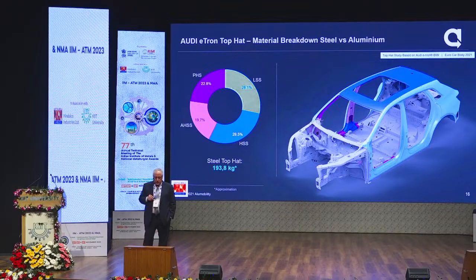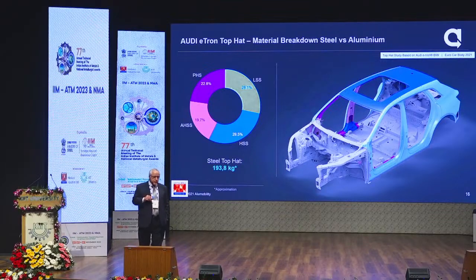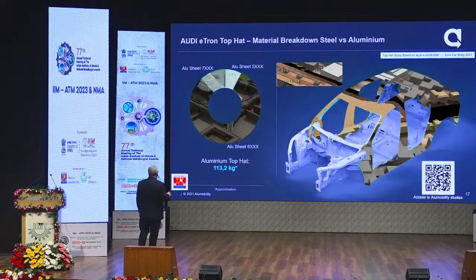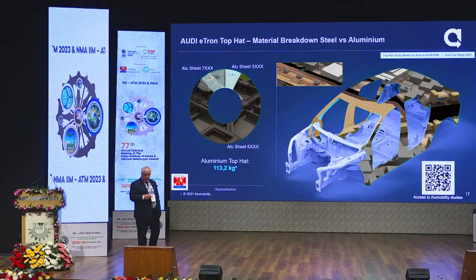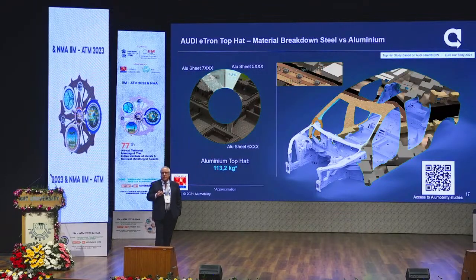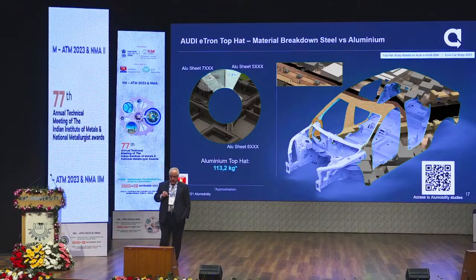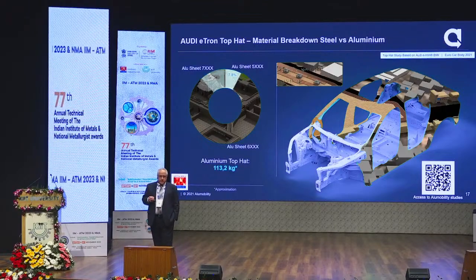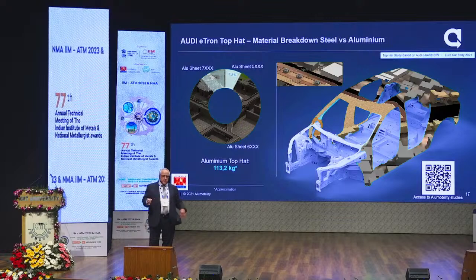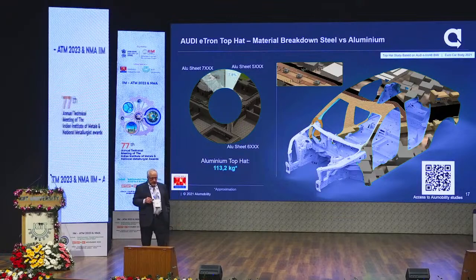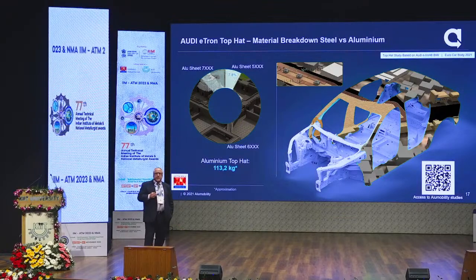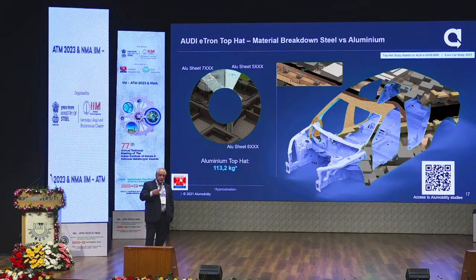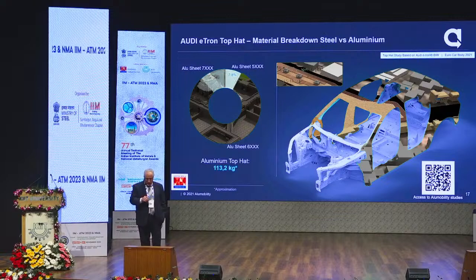First example, Audi e-tron top hat, super optimized in steel grades, 193 kilo for this top hat. Moving to aluminum, you see we go down to 113 kilo. And again, you see the weight saving. Everything I will tell you is between 40 and 50%. So in this case, 41% from a steel optimized solution to an aluminum solution, fully optimized.